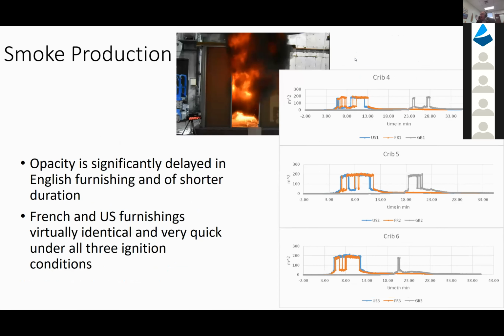So opacity measurement, you see the same sort of effect. You're at 23 minutes before you get any obscuration with the crib 4. It says 18 minutes and about 19 minutes for cribs 5 and 6. What that really means is the air is clear enough you can see your way out of the room, escape easily. It's a very important factor as far as escaping the building, what you can see to get out. So opacity here was delayed significantly for the UK room, which has the highest standard for fire retardancy in furniture, and obviously is a pretty good standard.